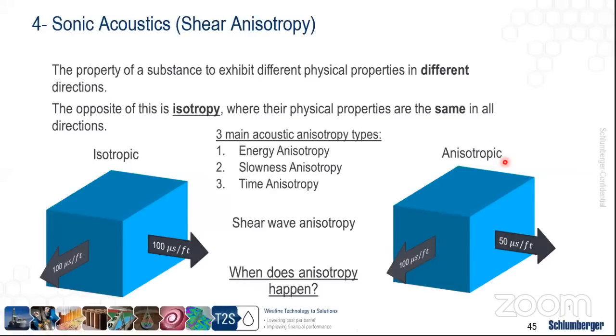So due to stresses, let's say, for example, I'm stressing the formation from this direction, I'm compacting the formation much more from this direction, I should be expecting to read a different slowness compared to this relaxed direction. So if we're applying stresses, by just looking at this difference in slowness in the different directions, let's say, for example, in X and Y direction, I can easily identify there's a stress regime here that needs to be quantified.